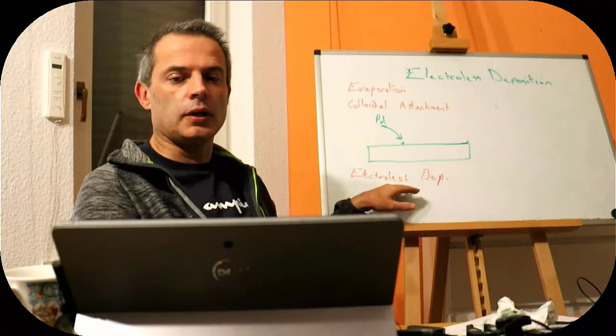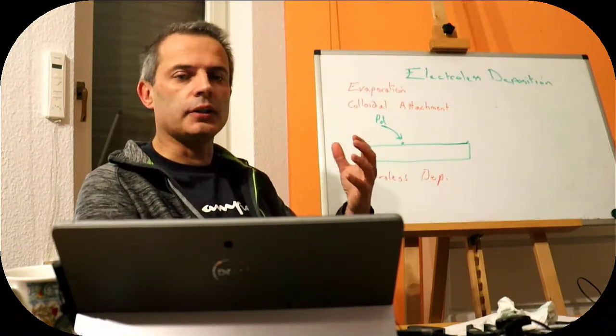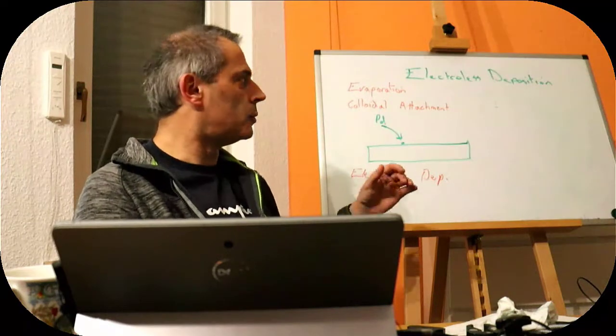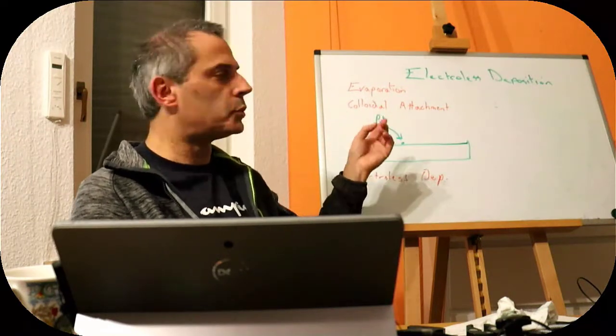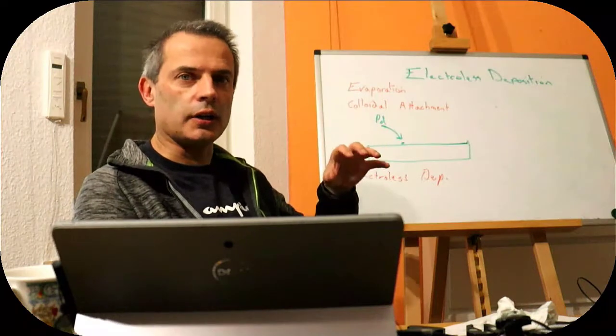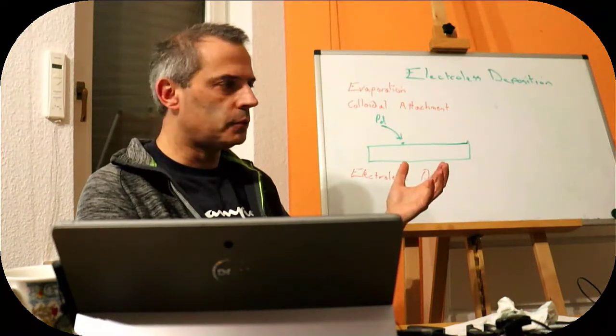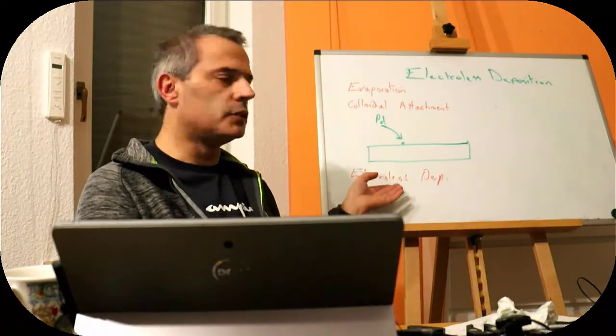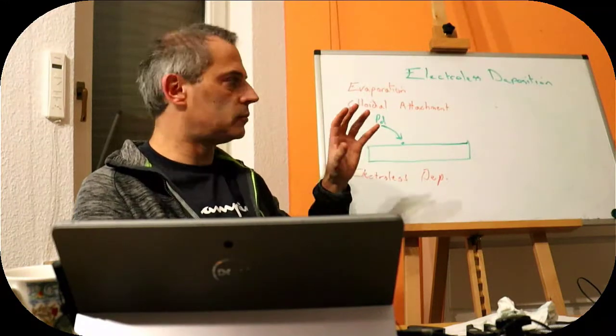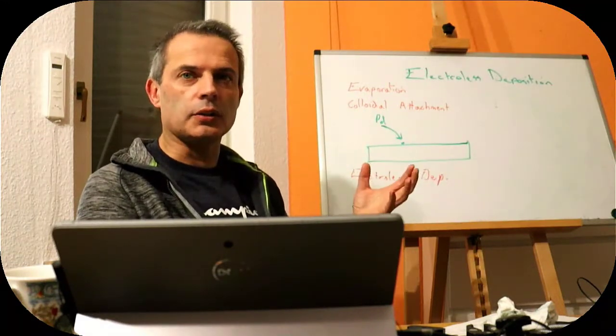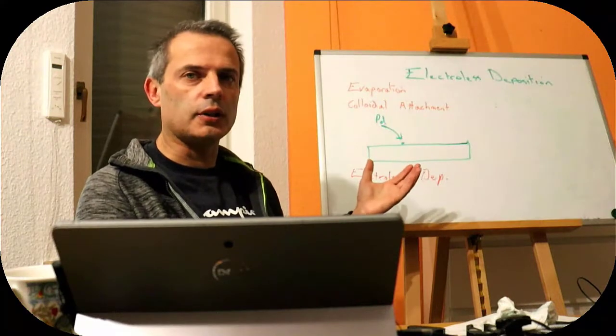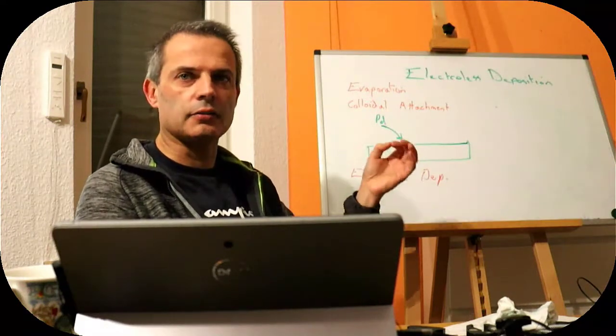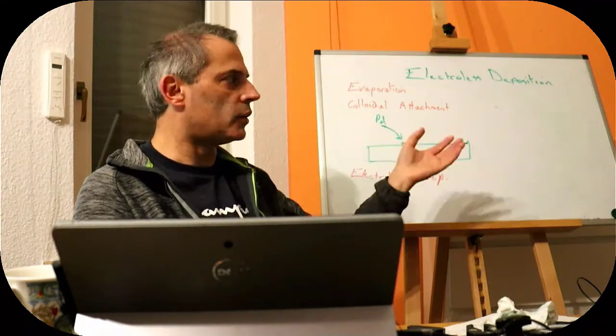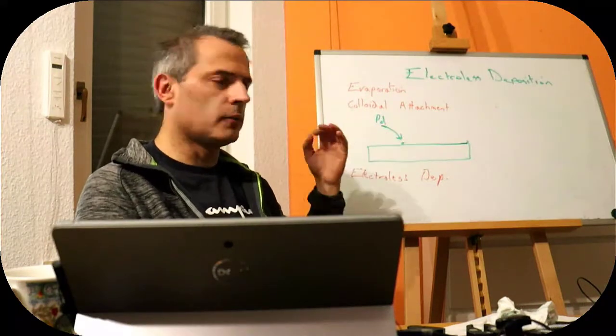So we could do an electroless deposition, but we're going to have to hit it harder. We're going to go further past the reduction potential to allow it to generate particles where it wouldn't normally do so. That means that if we do that, our electroless deposition solution is not going to last. We can't store it for any period of time, because it's going to be active and generate particles in solution and on the walls of the container deliberately.